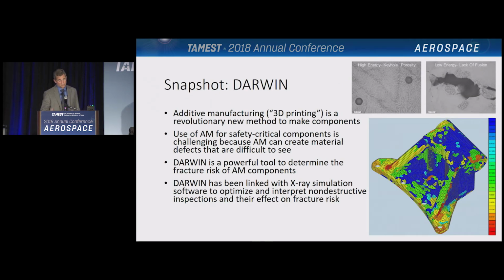One recent addition to the program is the ability to perform the fracture risk calculations in additive manufactured parts, which can be more susceptible to cracking than parts built using conventional techniques. Part of this functionality is the ability to link Darwin with X-ray simulation software to map anomalies within the material and determine the risk of them growing to failure.